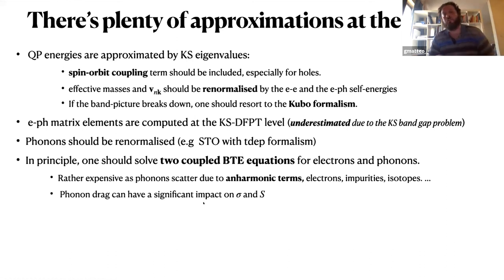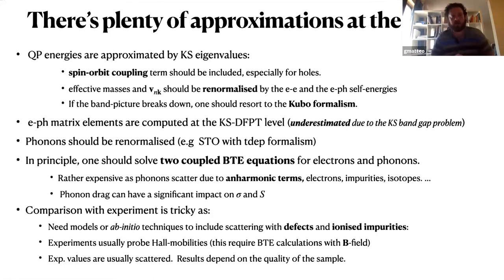And phonon drag can have also an impact on the conductivity and the Seebeck coefficient. And last but not least, also the comparison with experiment is tricky because one should include the effect of ionized impurities either through models or ab initio techniques. In experiment, usually they probe Hall mobilities and this requires some extension of the formalism to include the magnetic field. And also the experimental values are usually scattered because the quality of the sample strongly affects the electronic conductivity. So this is the last slide of my talk. I thank you for your attention and I will be happy to answer your questions.